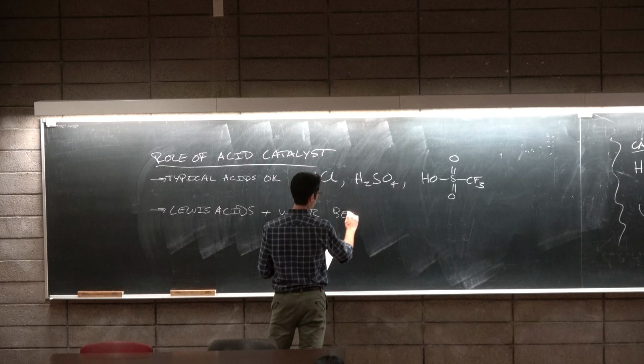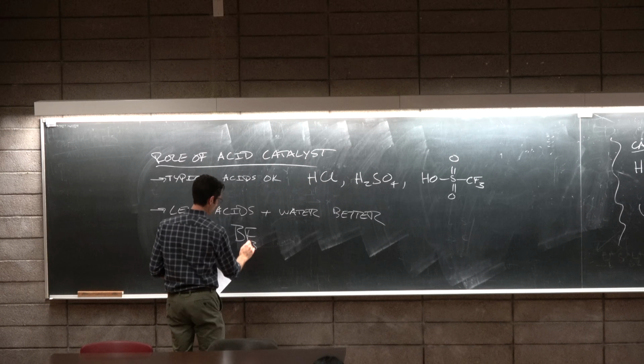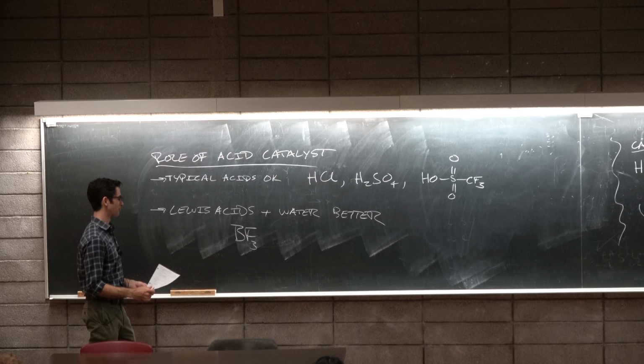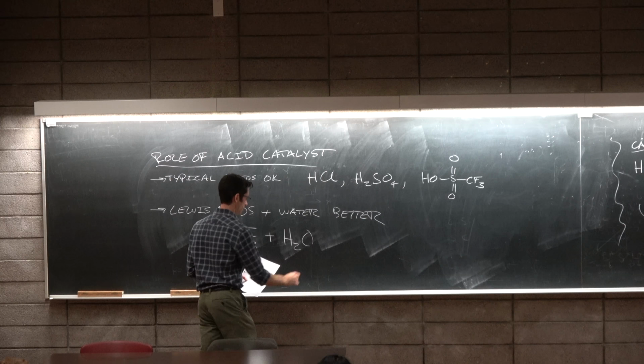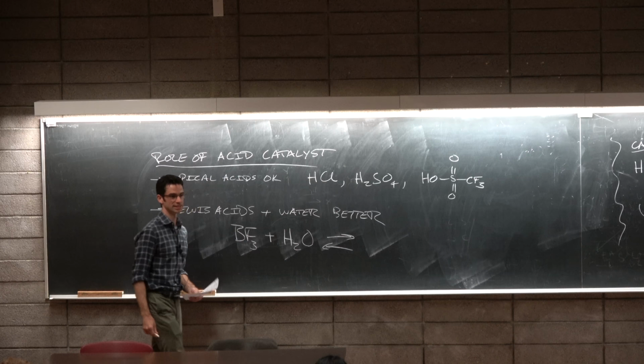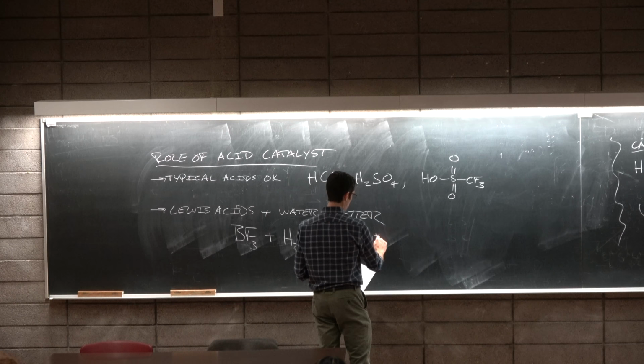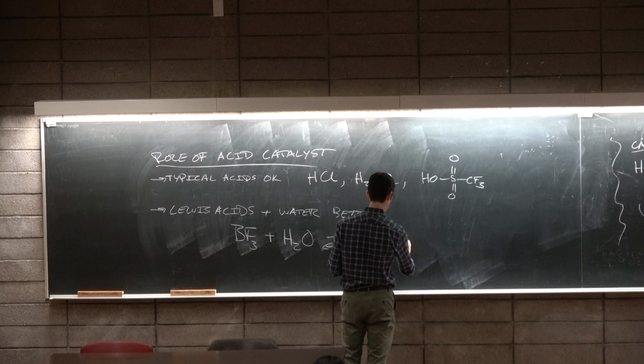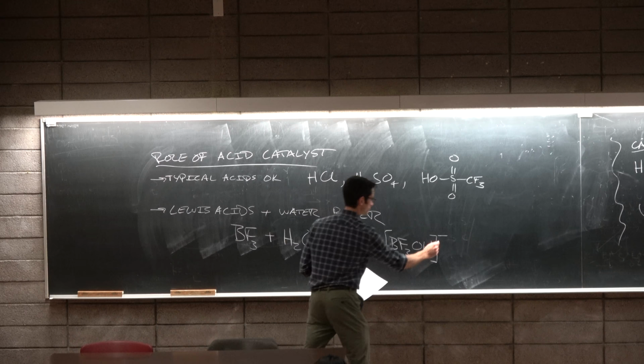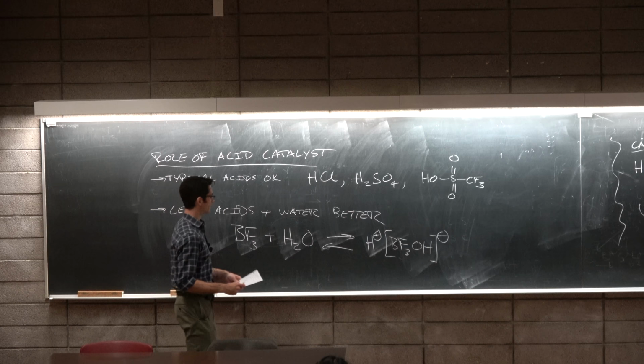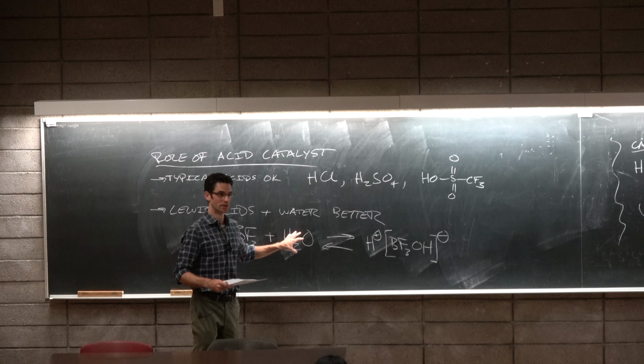So if we have BF3, boron trifluoride, or best friends forever, plus H2O. And there doesn't have to be a lot of water in the system, just enough to activate the Lewis acid. We get this super strong Lewis acid complex. And this is only activated in the presence of a little bit of water. The BF3 alone will not initiate the reaction.